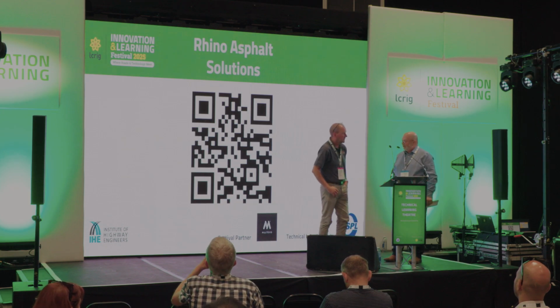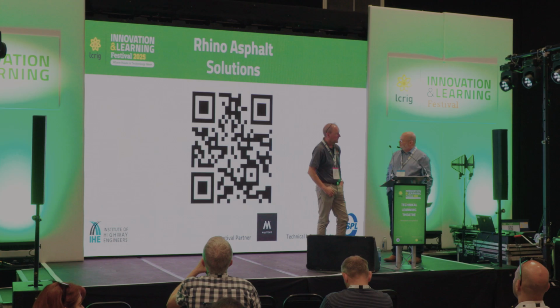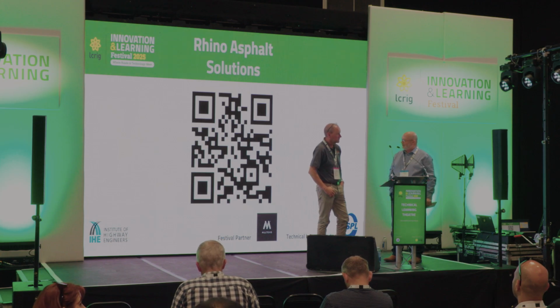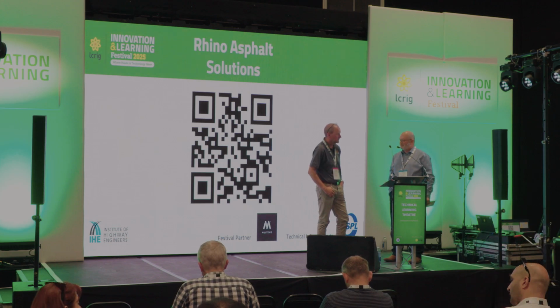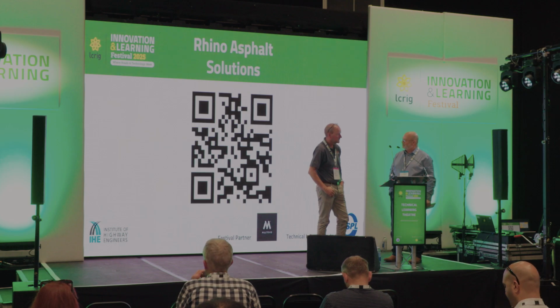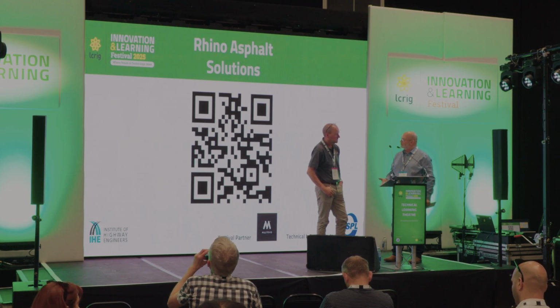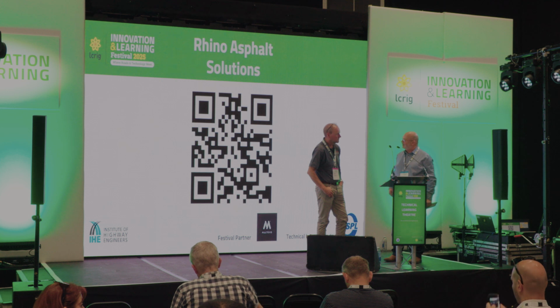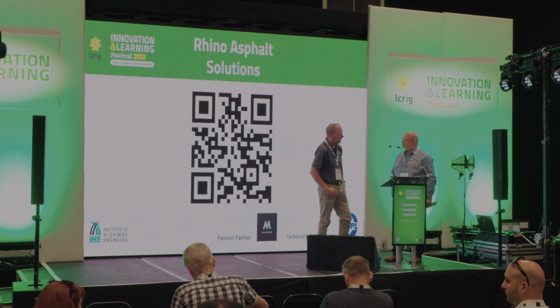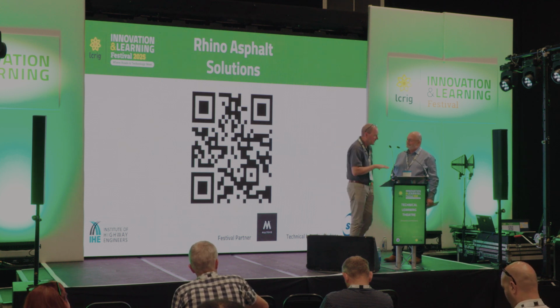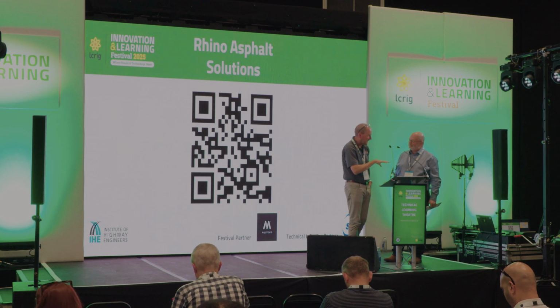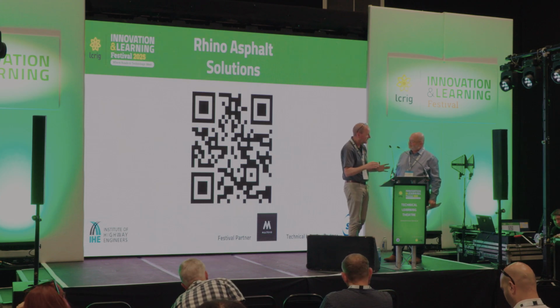No, only where the repair needs to be an inlaid treatment rather than an overband. So it's typically where there are multiple cracks that need to be treated. We may be going maybe 40 millimeters deep, and we need to then mill that out into the road surface. We've also, certainly in Cornwall, been using more of these mastic-type treatments for wider defect applications.